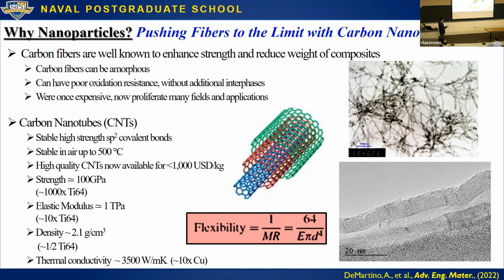The nanotubes themselves have very good mechanical properties. They have good thermal properties. They're lightweight. So all things that we like in a composite. Another interesting aspect of the multi-wall carbon nanotubes is that you get this so-called telescoping, or sometimes we call it sword and sheath mechanism. And you can actually get the interwall sliding between them. That's especially useful for ceramics where you're trying to impart strain tolerance onto the ceramic.